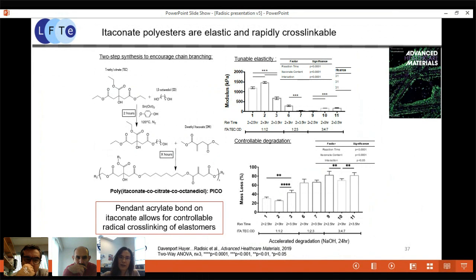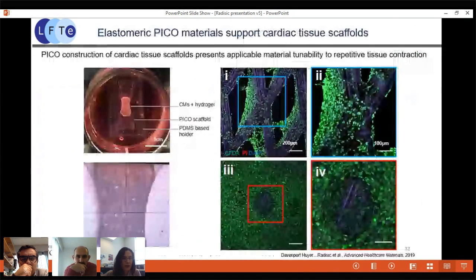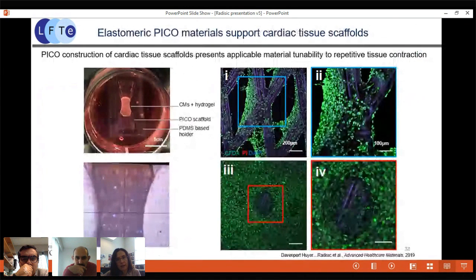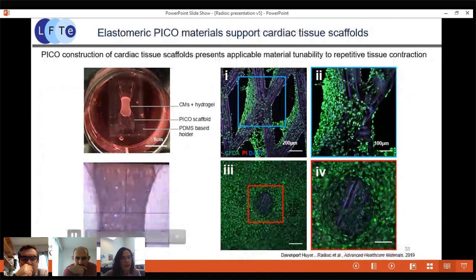And by doing that, you can see here how we are able to create a range of tunable mechanical properties, going from extremely soft polymers to hard polymers of over 1500 kilopascals. Doing that also enables us to tune percent mass loss, which is important if we want to have tunable degradation in vitro and in vivo as well. This work was published last year in Advanced Healthcare Materials, and you can see that these PICO polymers enabled us to create beautiful cardiac tissues that are beating quite strongly and that contain aligned cardiomyocytes.